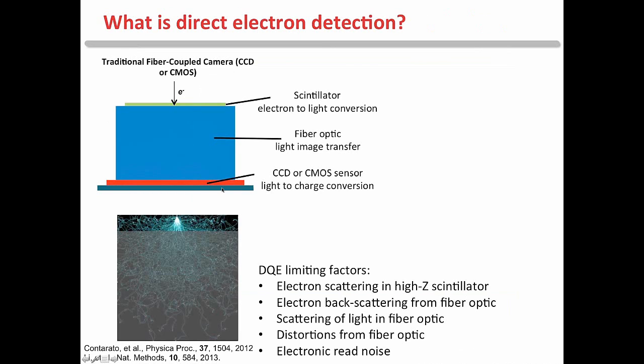The problems with this are, well, quite a number. First of all, you can get some scattering in the scintillator. It's a high Z material. You get backscattering from the fiber optic and scattering of light within the optic. There's distortions caused by that, as well as electronic read noise.